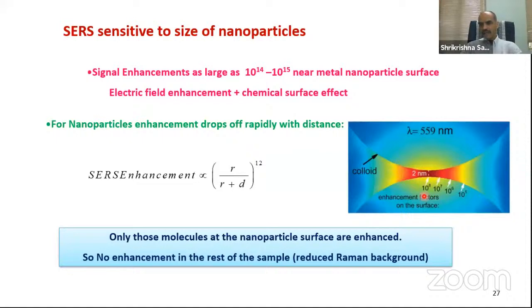You can see that when these two metal nanoparticles are close with each other, when the distance between these two is 2 nanometer, the electric field is of the order of 10⁸. If you come here, when the distance is slightly higher than 2 nanometer, you can see that the electric field decreases to 10⁵. So there is a 3 order of magnitude decrease in the Raman signal. I mean electric field, and obviously that will result in an intensity reduction of 3 orders of magnitude. So what does it mean? That the probe molecule needs to be very close to the metal nanoparticle surface.